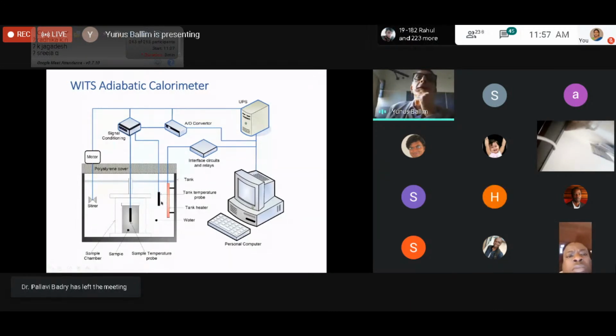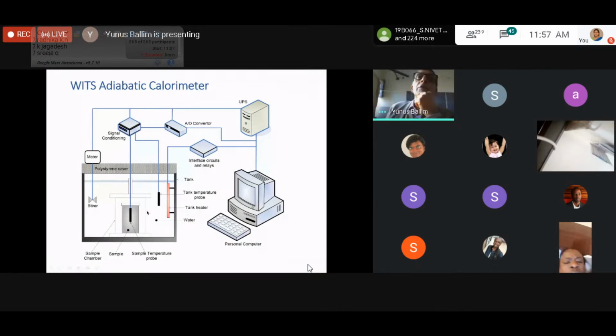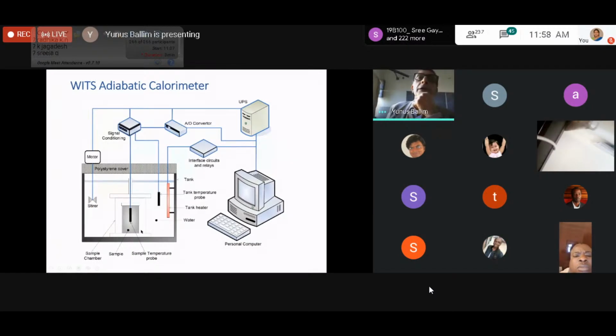And what happens is either the sample temperature is cooled because the water is not keeping up, or the water temperature chases the sample temperature. We solved that problem by adding a pocket of air around the sample to act as a dampening function in that harmonic response. And it sorted out the problem. Of course, it reduced our sensitivity slightly, but what it does do is sort out the problem with harmonic responses. And we get very good results out of this.